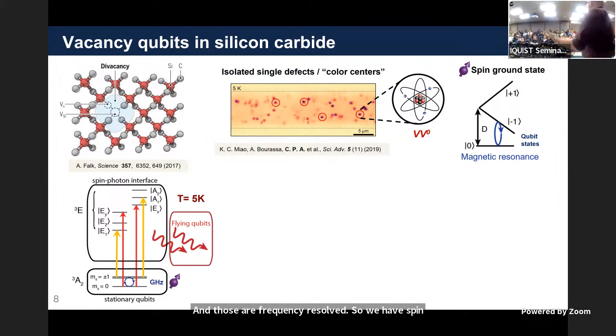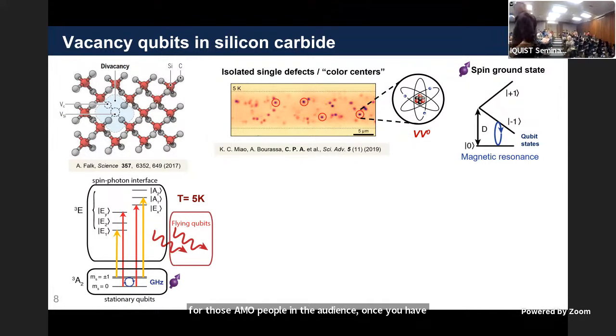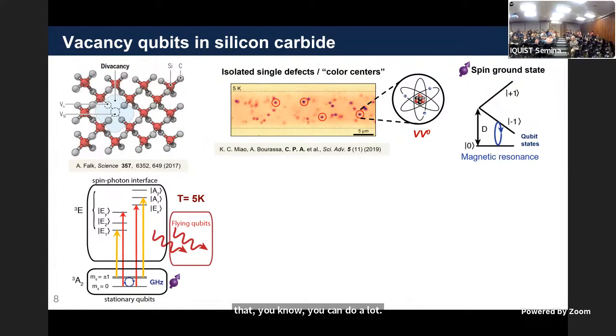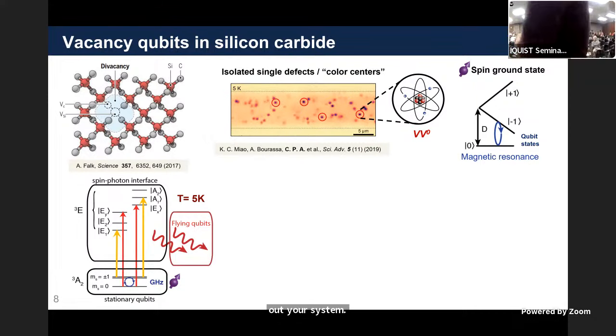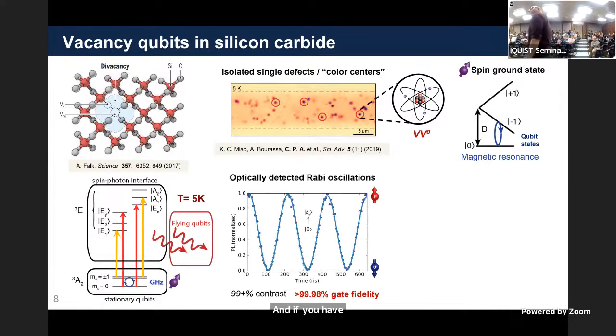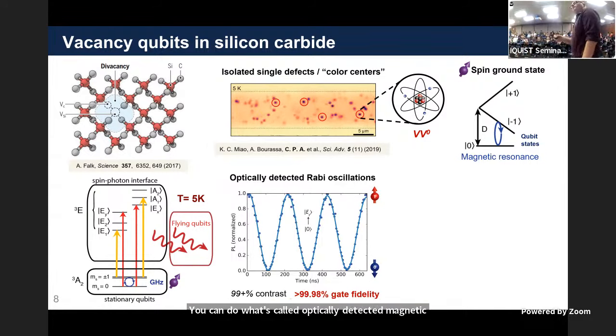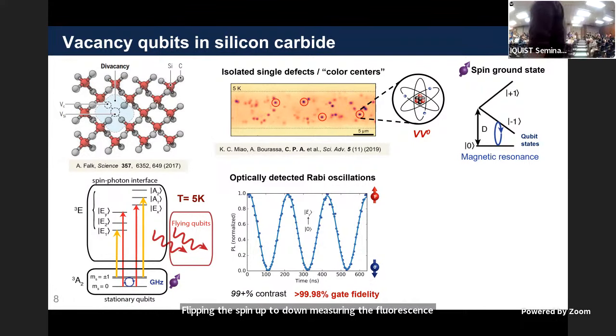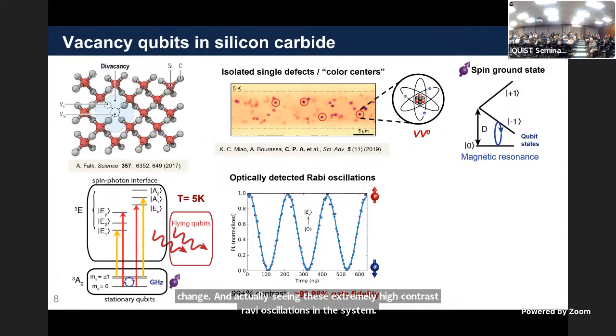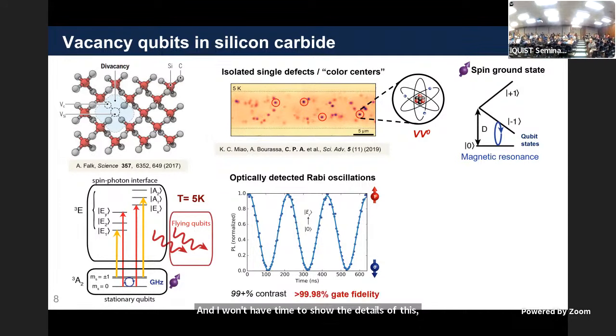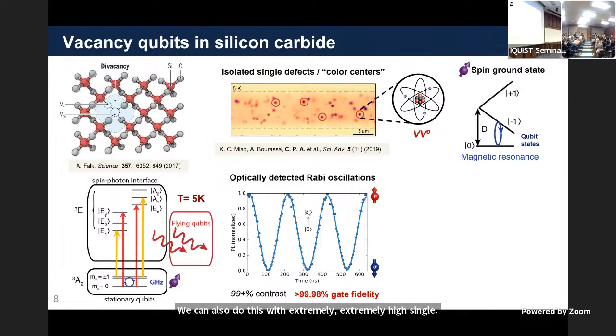So we have spin-selective, frequency-resolved optical transitions. And for those AMO people in the audience, once you have that, you can do a lot. You can pull all these tricks from atomic physics to optically pump and polarize your system, and optically read out your system. And if you have that combined with this ability to do spin resonance and manipulate the qubit, you can do what's called optically detected magnetic resonance or optically detected Rabi oscillations, flipping this spin up to down, measuring the fluorescence change, and actually seeing these extremely high contrast Rabi oscillations in the system. And I won't have time to show the details of this, but we can also do this with extremely high single-qubit gate fidelity, approaching four nines. So we have extremely good control and readout of this system.